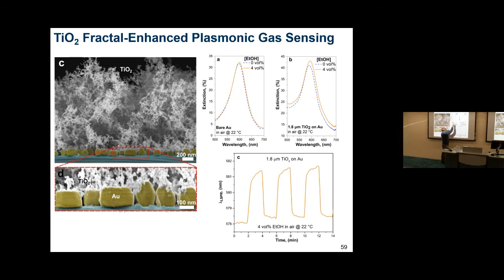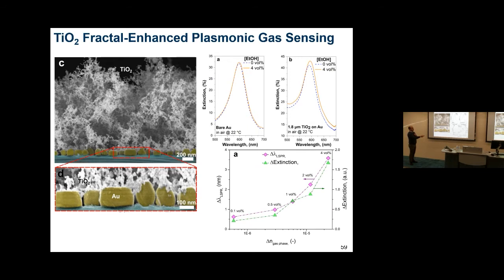This was just the gold, and this is the gold with the titanium oxide fractal nanoparticle. You see a big shift at the same concentration, and suddenly you're able to detect 4% of ethanol, and actually much lower. We could go down to 0.1% with quite a large shift in the resonance frequency, down almost to, at 0.5%, we have about 1 nanometer. So this is not too bad.